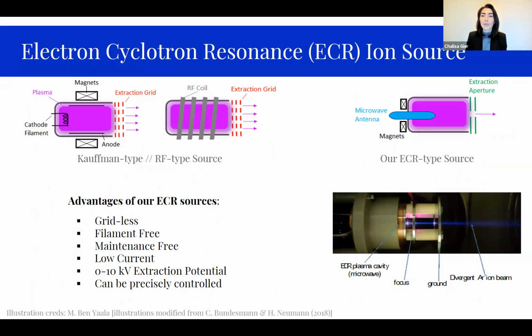In a typical ion beam deposition system, either a Kaufman type or an RF type sources are used. With these sources, the ions are extracted and accelerated using a grid system, which is a source of contamination for coatings. Whereas our system, we use ECR type sources. How this works is that a plasma is created by the help of a permanent magnetic field and a microwave, where free electrons can absorb the microwave power and continuously accelerate and ionize the gas molecules that was injected. This happens when the microwave frequency matches the angular frequency or the resonance of the electrons. The beam is then extracted through an aperture rather than a grid.